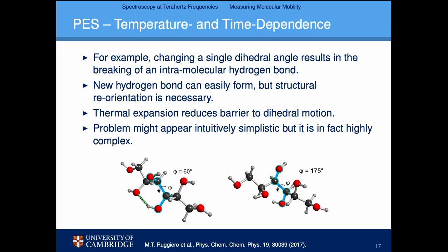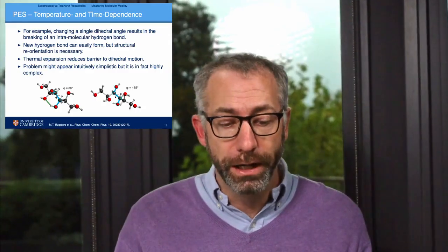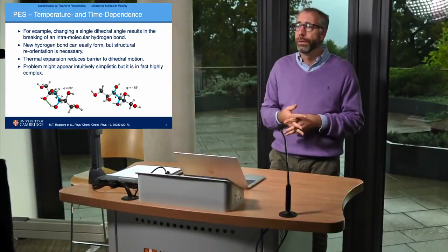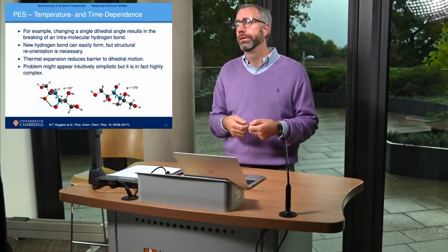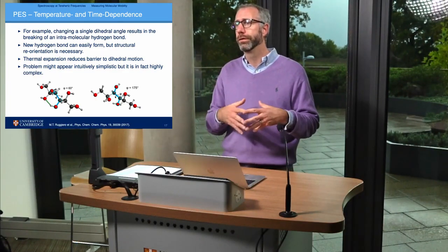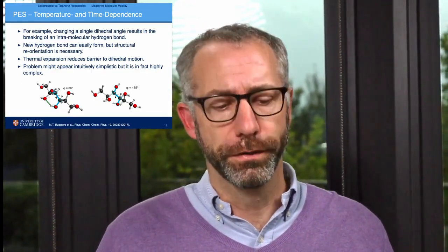While this phenomenon is associated with overcoming potential energy barriers, the origins are slightly more complex, as the barrier heights, and indeed the entire potential energy surface itself, are equally dynamic as the processes themselves. Now, this arises because the potential energy surface, which dictates the atomic dynamics and the structure, evolves in time as the interactions themselves change, with various factors influencing the structure at any given time.